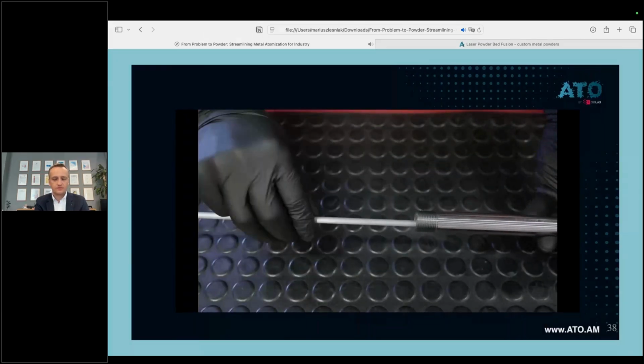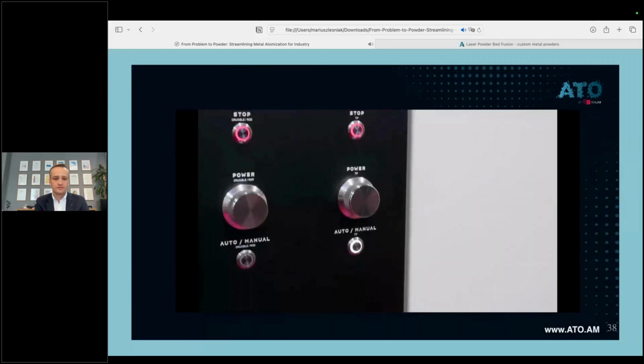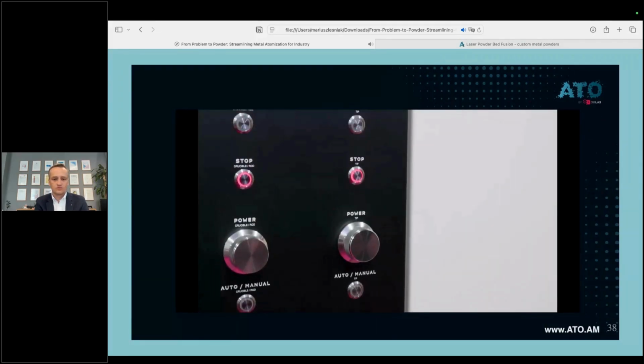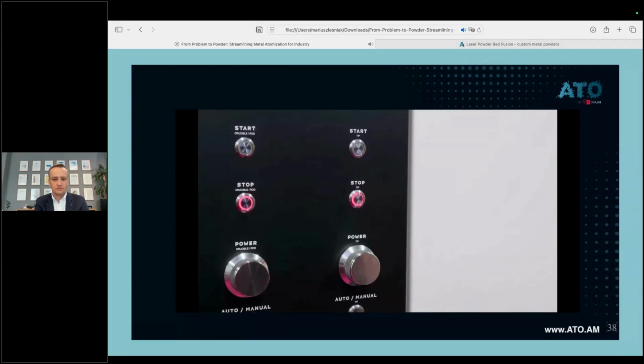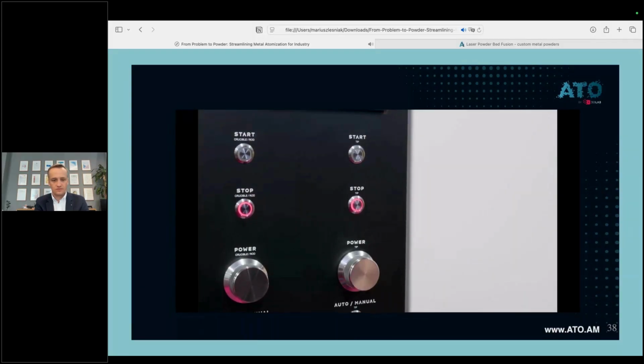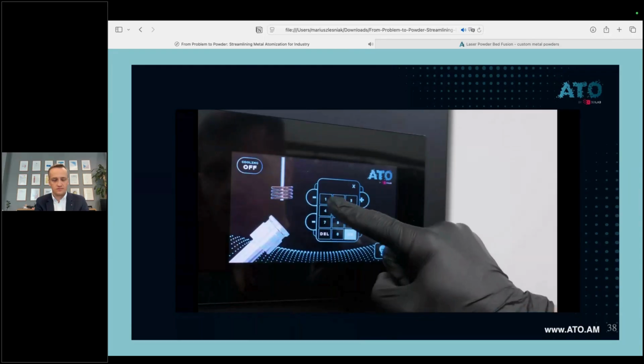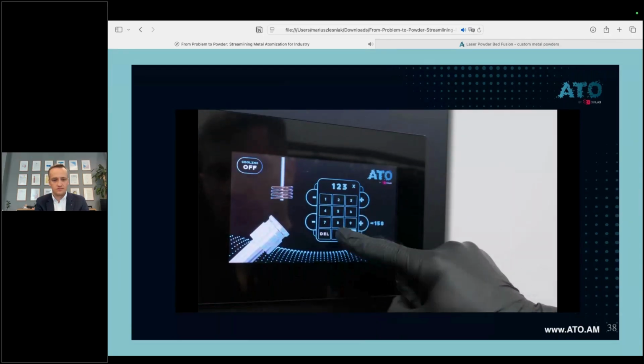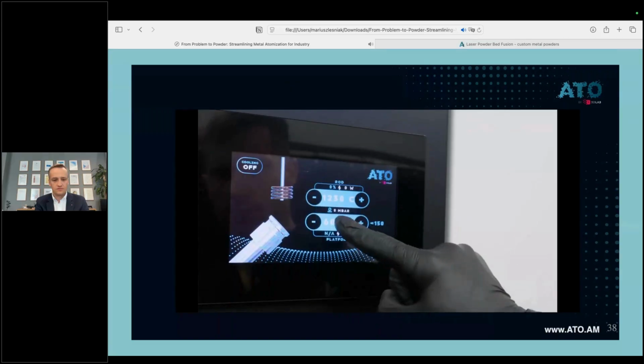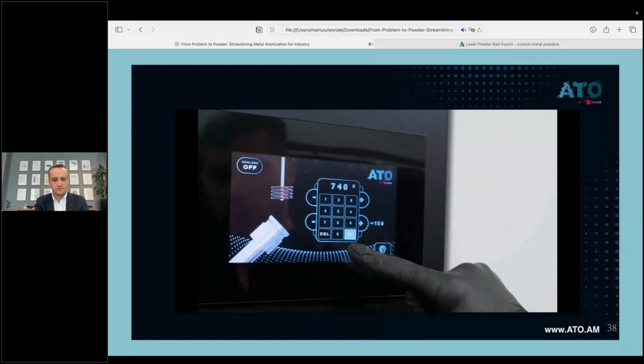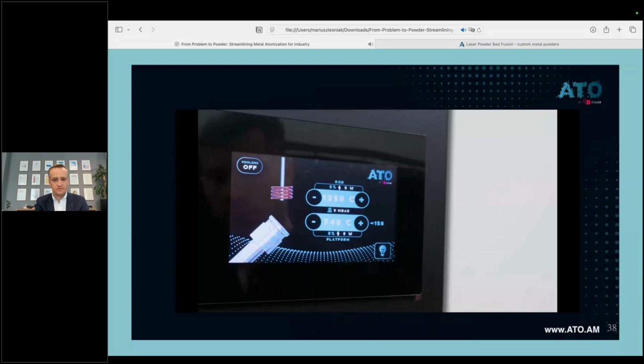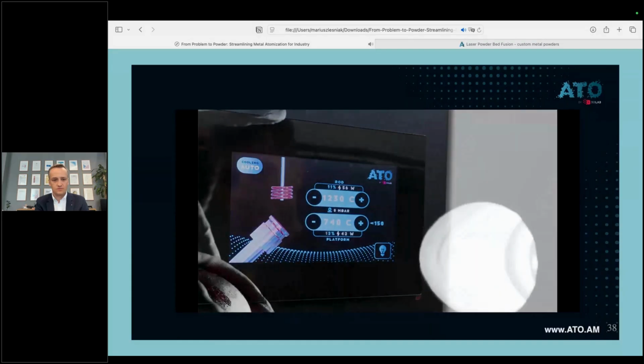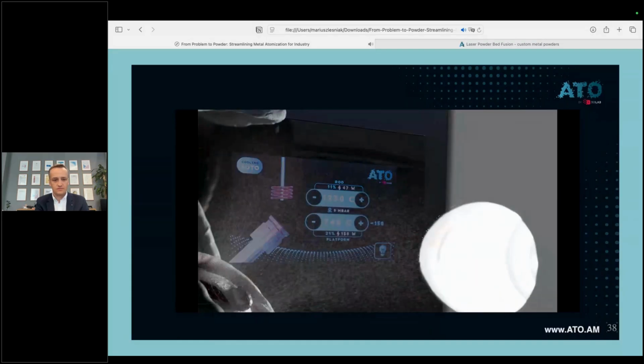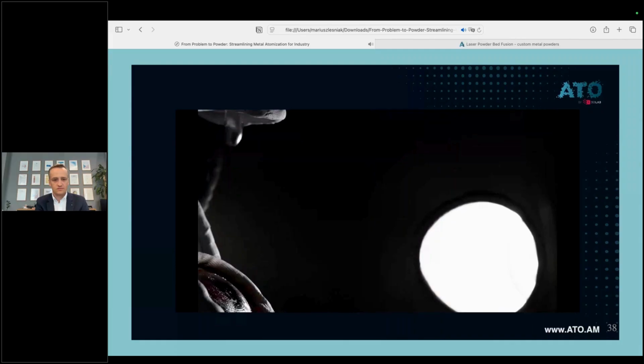Expand your range with the induction melting system, perfect for atomizing metals with lower melting points. When combined with rod-based feeding, it enables fully contactless powder production, ensuring maximum chemical purity. The IMS uses induction heating to warm both the feedstock and the atomization platform, providing a stable, efficient process. Atomization is carried out on our patented ultrasonic tip, which ensures consistent droplet formation and excellent powder sphericity.